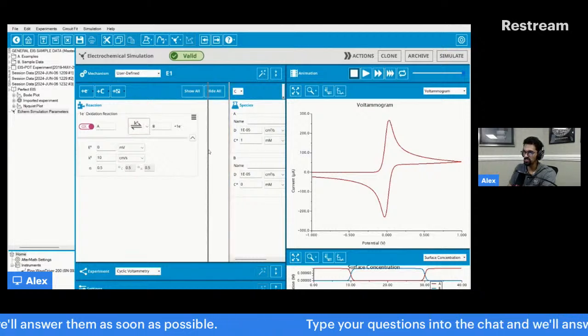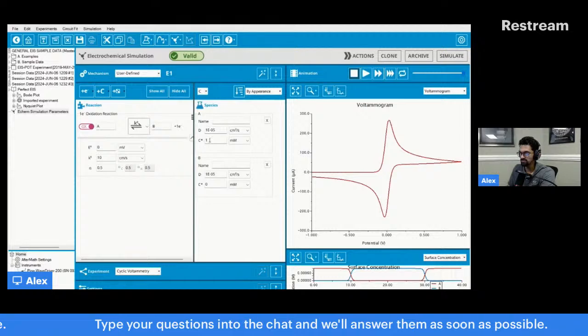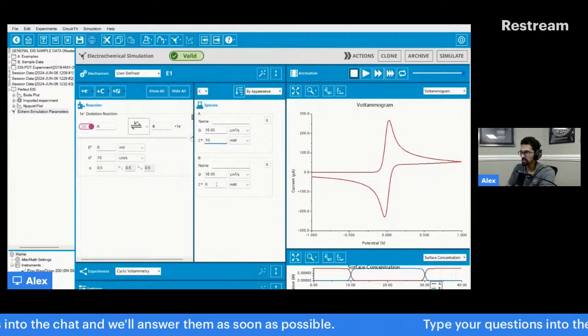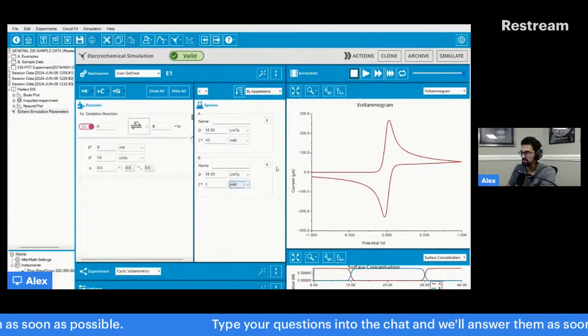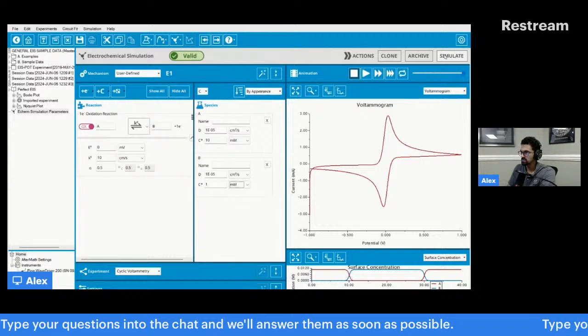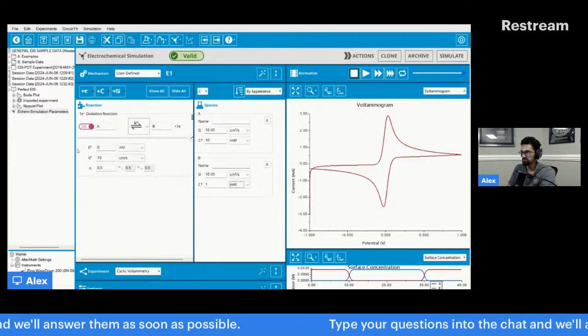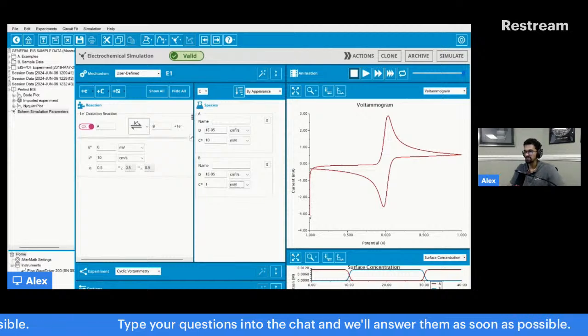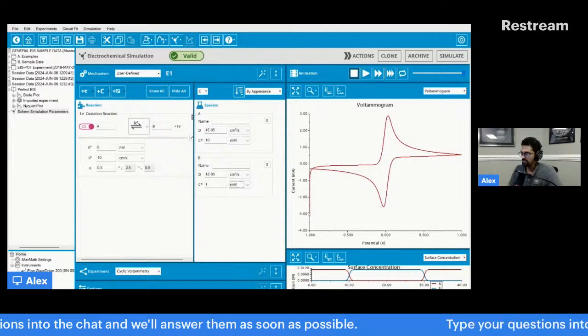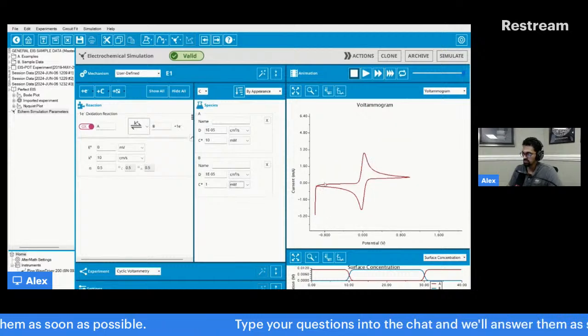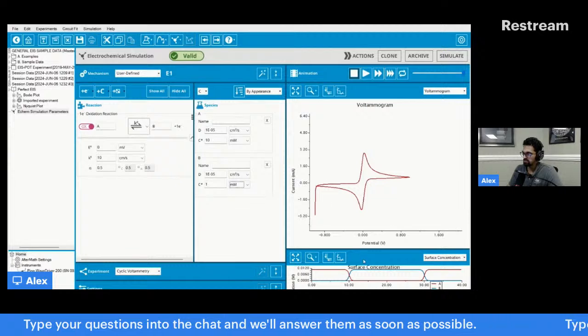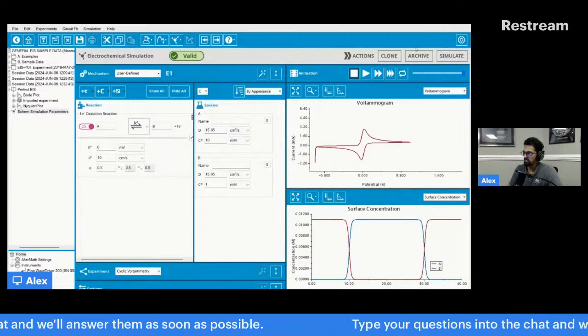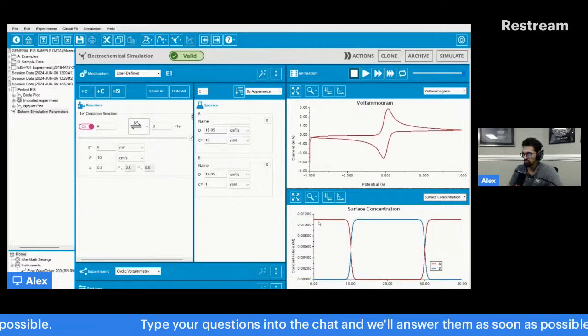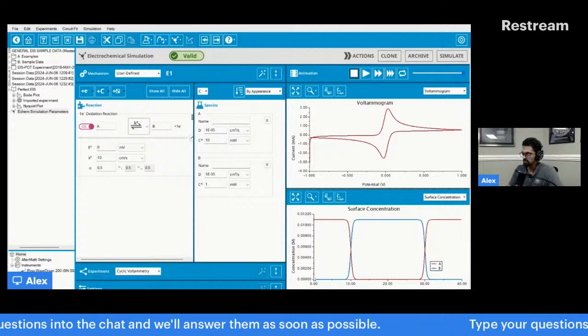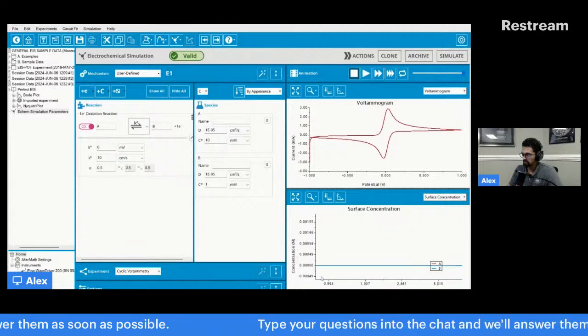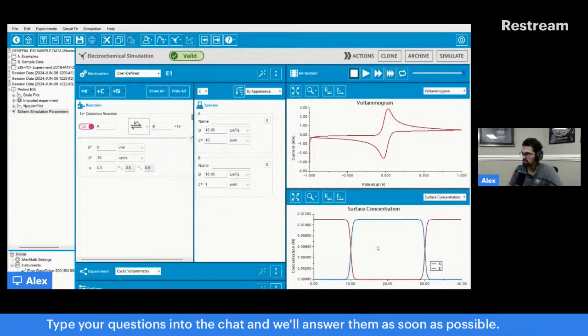Now, right now, this is a situation where I only have A, but I can mess around with this when I have 10 times the amount of A as B. In this case, I need to have some B in the system for this to work. So if I simulate this, this is what I get. It turns out that if this is a reversible reaction, some of the B is actually going to be reducing, going back here. So the current actually starts here and it goes this way first. So all of this B is getting reduced. And in the concentration profile, these start to get switched. So A is red and it's full, but B, you can't actually see it. I may have to double check that, or maybe if I zoom in close enough. But it's interesting that B does not show at time equals 0.